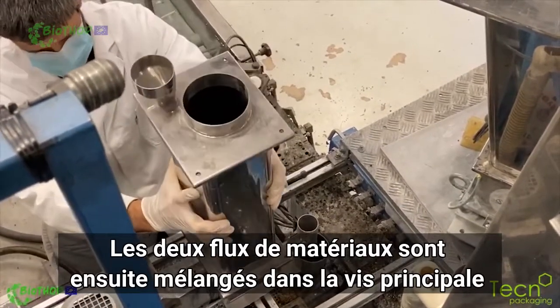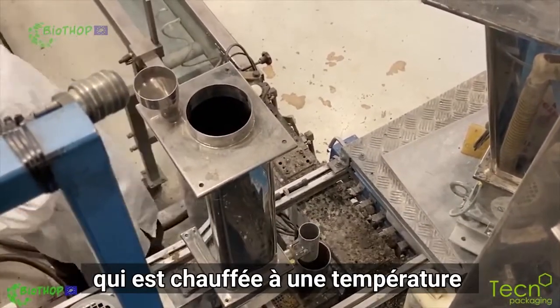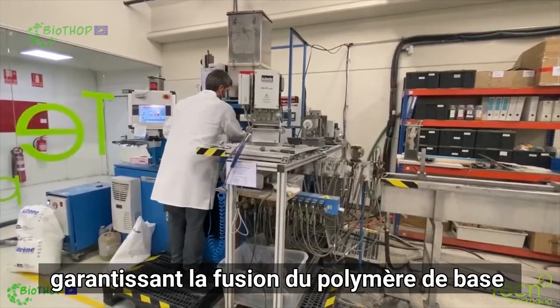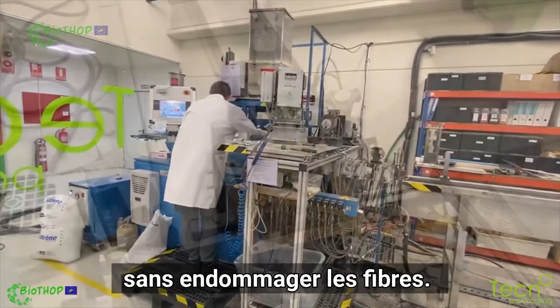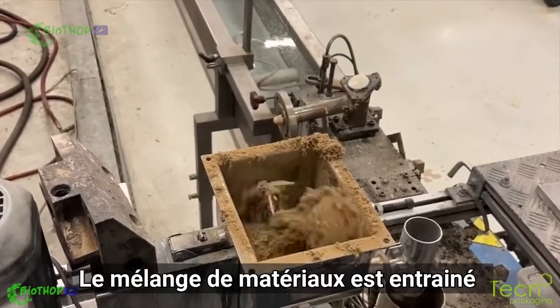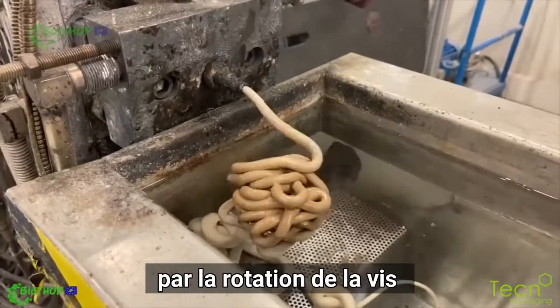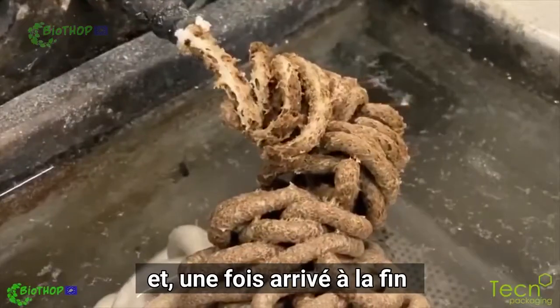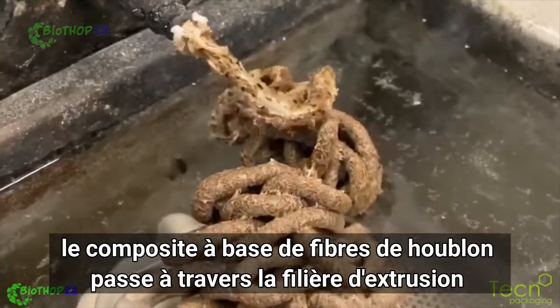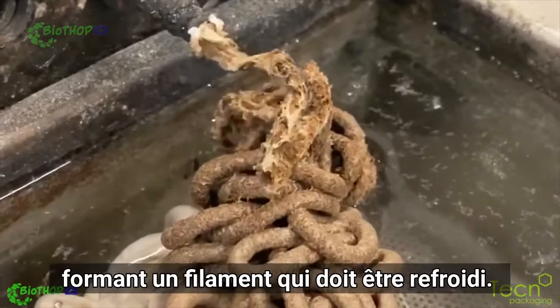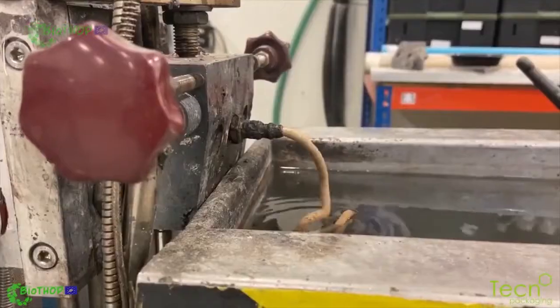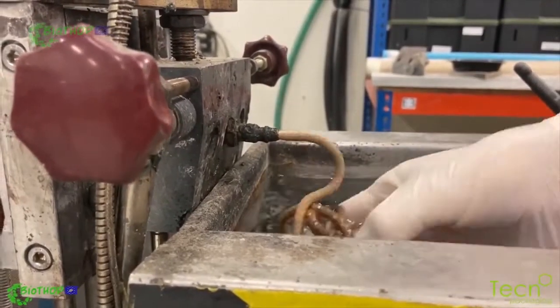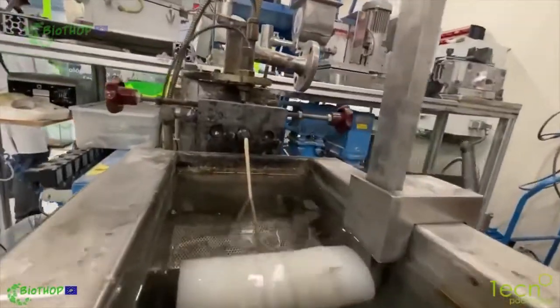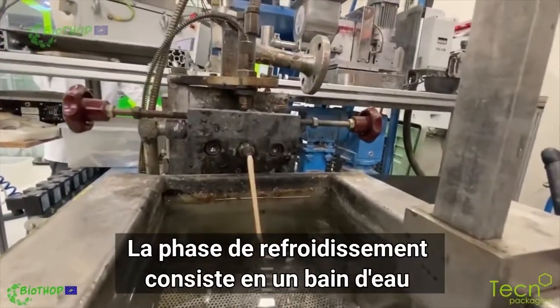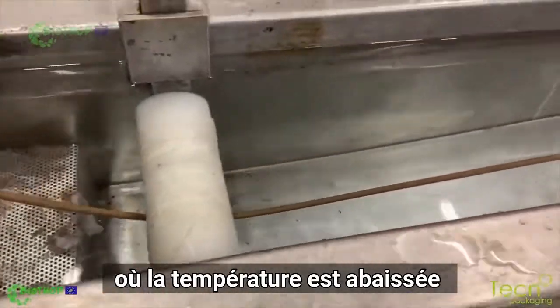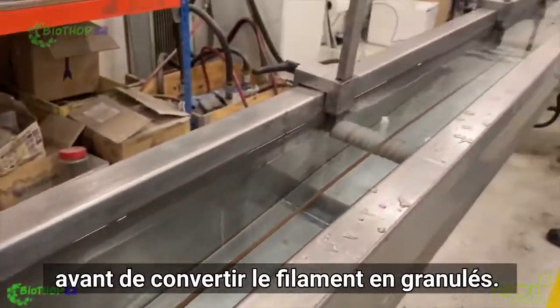Both flows of material are then mixed in the main screw, which is heated to a temperature that ensures the melting of the base polymer without damaging the fibers. The mix of materials moves forward by the rotation of the screw, and once it reaches the end, the hop fiber-based composite passes through the cylindrical die, obtaining a filament that needs to be cooled down. The cooling phase consists of a water bath where its temperature is decreased before converting the filament into pellets.